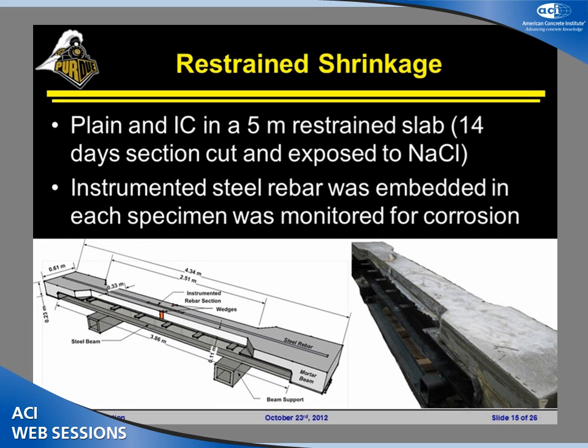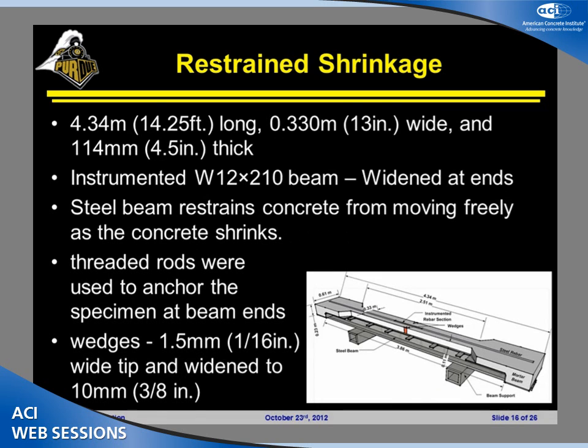They're on a restrained element. This is roughly 14 feet long, 5 meters long. It's a fairly substantial beam that's underneath here, and I'll give you the dimensions in a second, but it's a very, very stiff element. So we've got a high degree of restraint in the system, and we're going to place an instrumented rebar right down the center here, so that we can start to monitor a few things about corrosion.